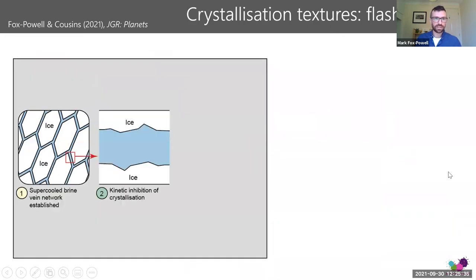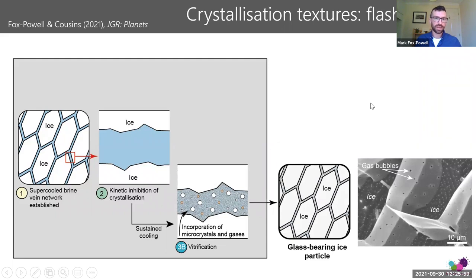By contrast, we have a very different scenario when we cool very rapidly. We still have the establishment of this brine vein network as I showed in the SEM images, but here the cooling rate is so rapid, and the accumulation of solutes is so high, that we inhibit crystallization within those brine veins. Now, what happens next is really a consequence of the subsequent thermal environment that those particles experience. So if rapid cooling is sustained, like in our experiments, we go on to vitrify, we solidify that brine as a glass and end up with this glass-bearing ice particle.